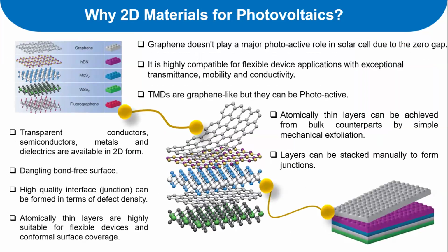They mimic the graphene structure, but their application is beyond graphene. Unfortunately, graphene doesn't have an optical band gap, so it doesn't absorb much energy in the solar spectrum, particularly the visible spectrum. So we cannot use graphene as a major photoactive semiconductor or photoactive material in photovoltaic technology. In that case, it goes as a semi-metal. So it is being used as an electrode, particularly a transparent conductor. We cannot consider that as an active semiconductor material. So though the hexagonal honeycomb structure is there, it is not that useful.